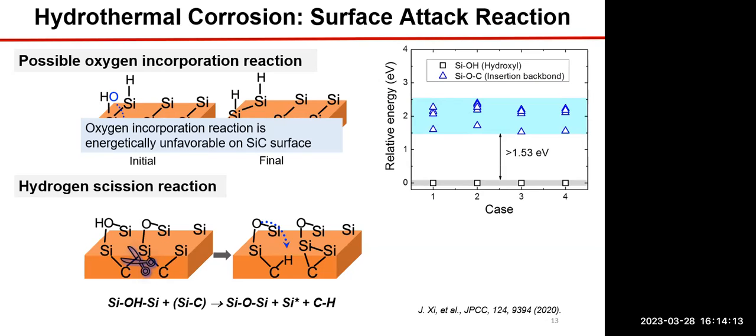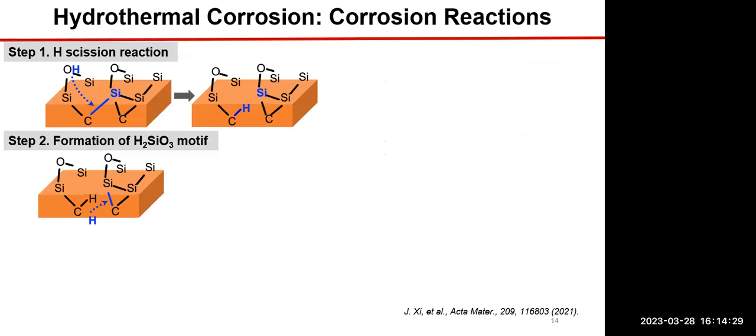This is very interesting, because we normally thought that hydrogen can stabilize the surface and passivate the dangling bond on the surface. But here we found that the hydrogen will damage the surface bond and break the surface. In our simulation, we further found the additional hydrogenation reaction will tend to break the silicon-carbon bond, and then it will displace the silicon atom outside the surface, as shown here.